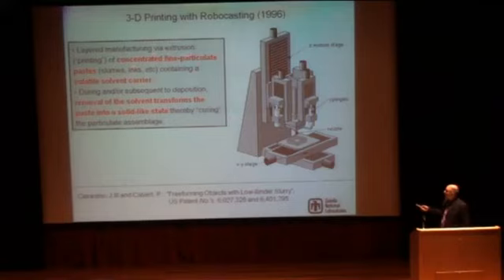The important thing is that it's a concentrated, very high solid, fine particulate paste that is carried in some volatile solvent, like water or alcohol or ketone. And then during the deposition process, the removal of that solvent, just a little bit, will transform the paste into a solid-like state. So we're not curing the ceramic by freezing or by laser sintering or anything like that. We're, quote, curing it by just changing the solids loading a little bit and changing the rheology.